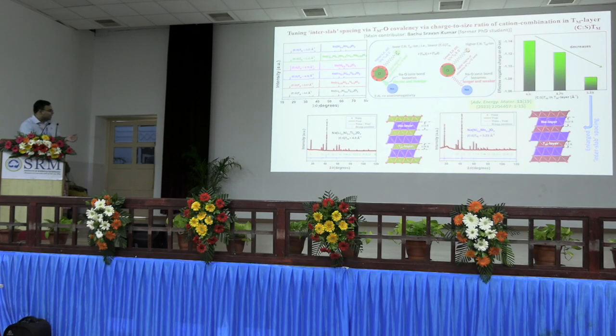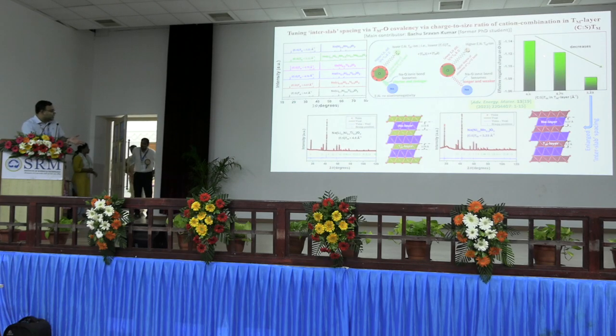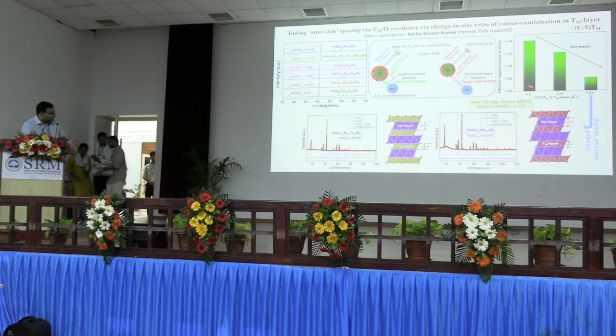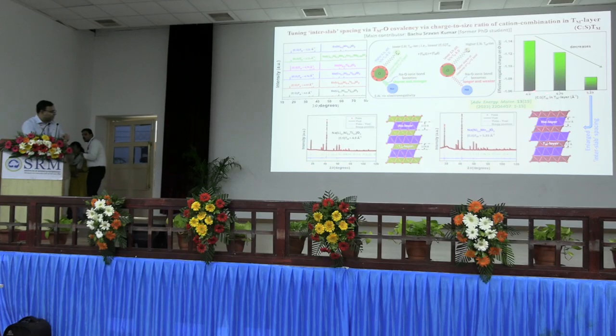Now DFT by my colleague at IIT Bombay, Abhijit Chatterjee, also showed that when the charge to size ratio of the cation in the transition metal layer is lower, the effective negative charge on the oxygen ion is more, which means my sodium oxygen bond will be stronger.